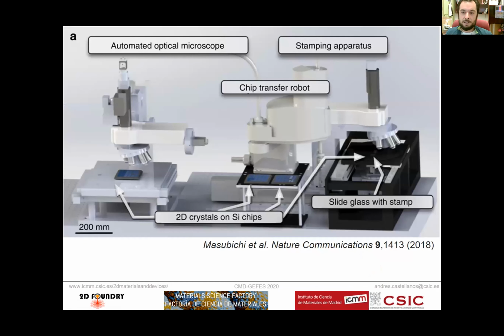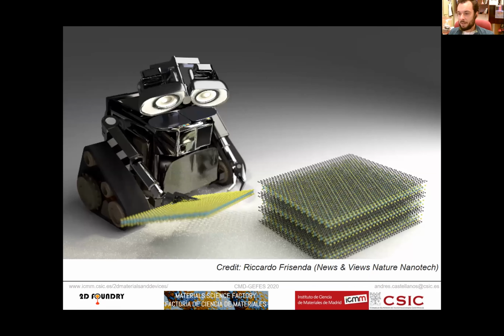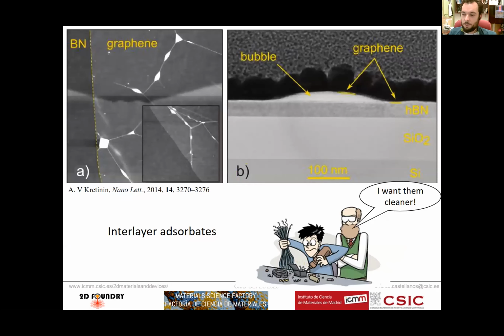Of course, there are nowadays new ways of doing this kind of assembly. A Japanese group has proposed a robotic setup to do this assembly of heterostructures. It looks like this, but we like to think about it in a more tender way, as our little robot piling stacks of materials on top of each other. But even with this robotic assembly, you will always find a problem with interlayer adsorbates. When you do this stacking process, there is a chance that you trap adsorbates in between the layers, and no matter what you do, you will get some of these bubbles or blisters. Depending on how good your transfer is, the density of these blisters will be larger or lower, but you will always get interlayer adsorbates. And for certain applications, the PI wants these heterostructures cleaner, right?